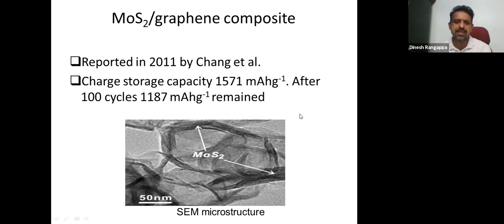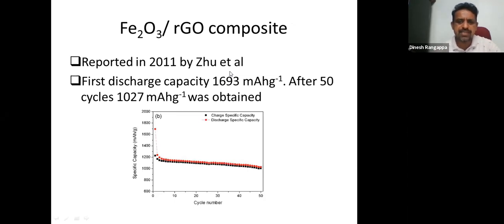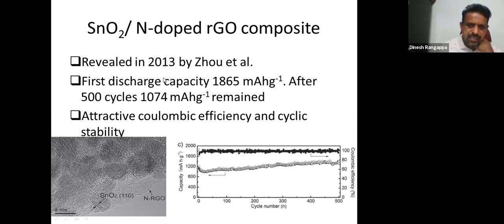And in our case, for molybdenum disulfide we could achieve up to 800 milliampere per gram capacity. And there is still scope for improving this capacity when we compare to this report. Similarly, iron oxide and RGO composite was reported with first discharge capacity up to 1690 milliampere per gram. After 50 cycles, it is stable around 1027 milliampere per gram. Similarly, tin oxide and nitrogen-doped RGO was also reported with a high capacity up to 1865. After 500 cycles, it still gives around 1000 milliampere per gram.